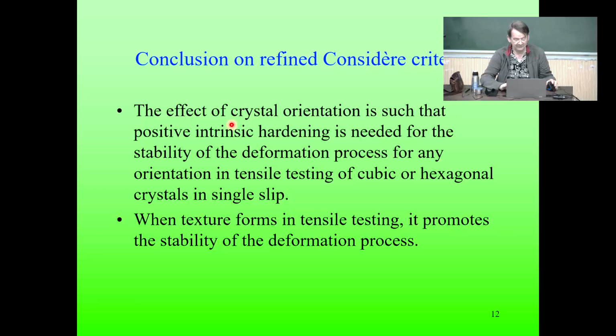So this is just a kind of introduction for you on the general topic of instability of deformation. Considère is really very well known, but this work is not well known, what we did with Professor Stüwe: it can be shown that an intrinsic positive hardening is needed in any case for the stability of the deformation in both cubic and hexagonal crystals in single slip, and when texture forms in tensile testing, it promotes the stability of the deformation process.